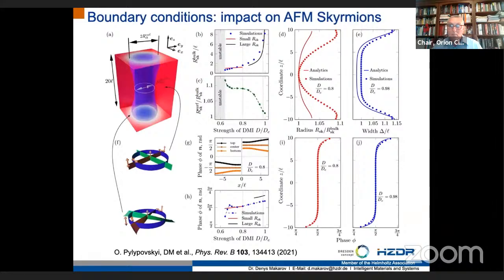For example, in this case, you have a Bloch-type skyrmion stabilized in an antiferromagnetic slab. Upon approaching the surfaces, the skyrmion string becomes broader, and also the phase of the skyrmion changes. It means that instead of a Bloch skyrmion like in the interior, you will have a mixed Néel-Bloch skyrmion at the surfaces. What is important to mention is that the domain wall and the skyrmion have a modification over several exchange lengths